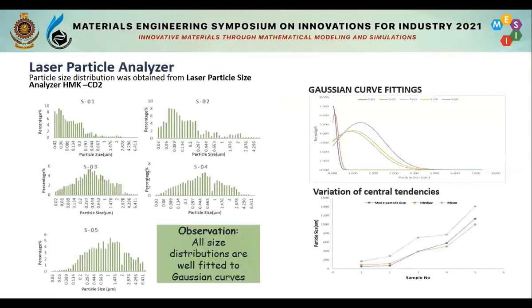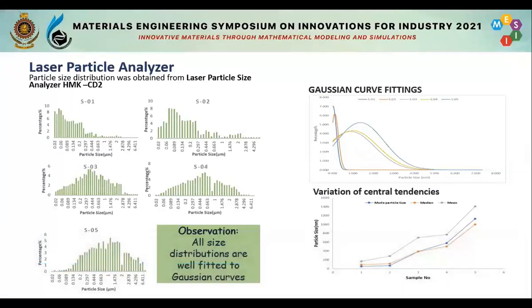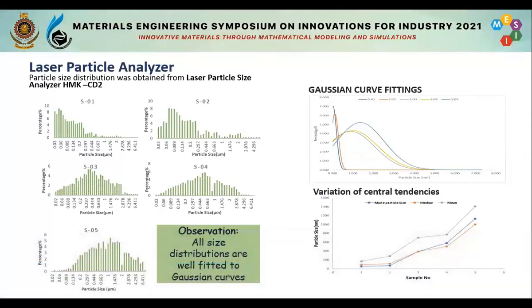Then we did the experimental validation. In the experimental validation, basically the laser particle analyzer was predominant. Here, we saw a normal distribution for each and every sample. Basically, sample number 1 has the narrowest particle size distribution, while sample number 5 shows the broadest distribution with respect to sample number 1. Going from sample number 1 to 5, we see a particle size increment in the size distribution.